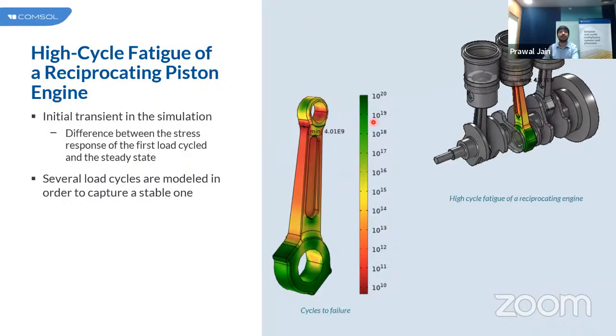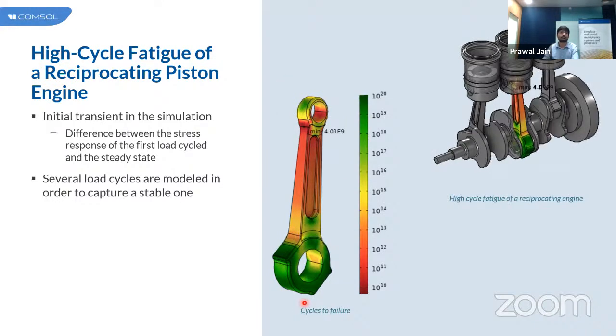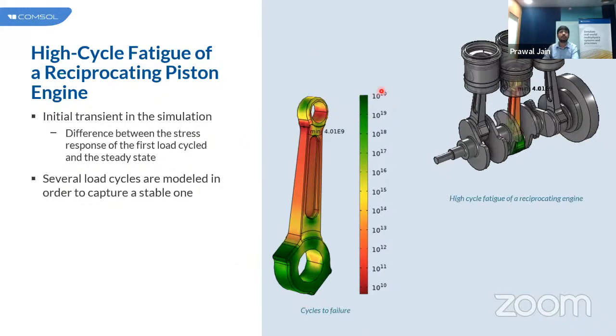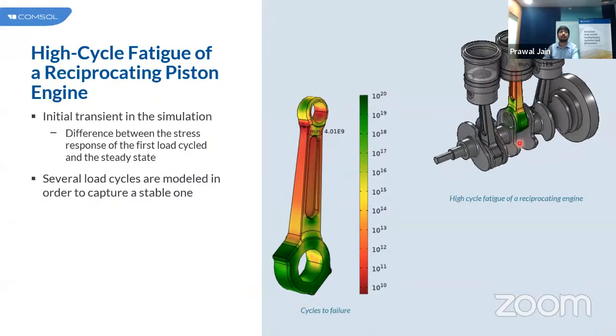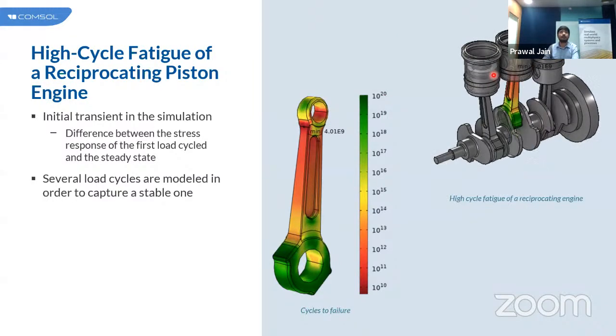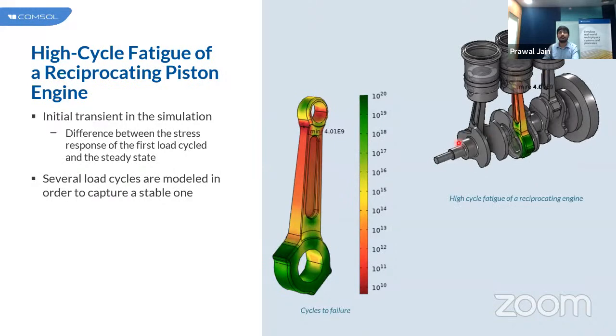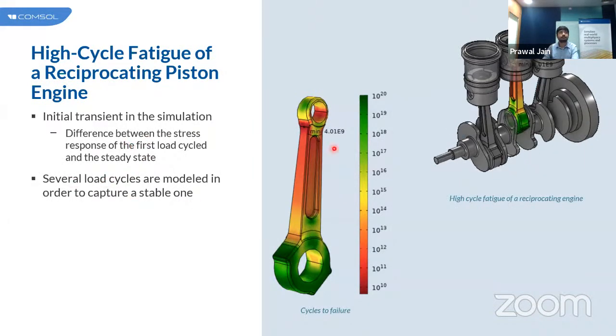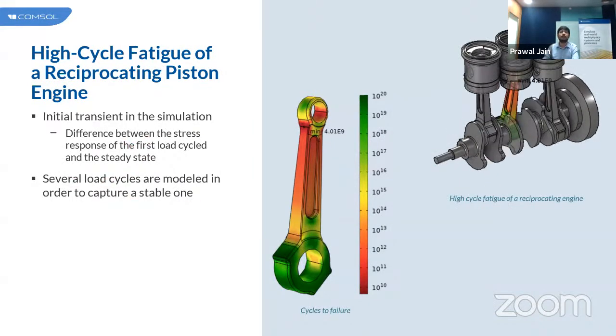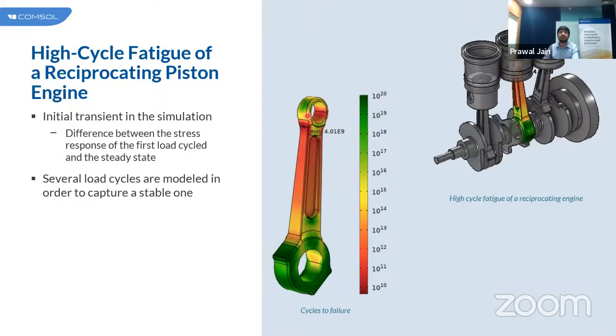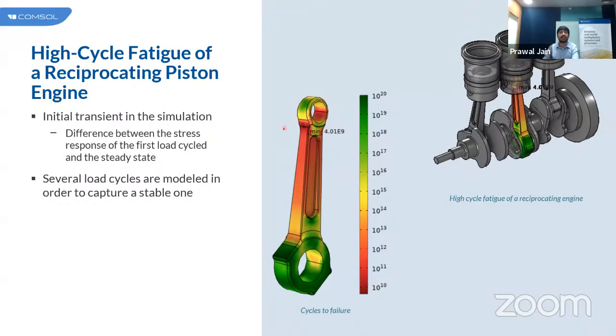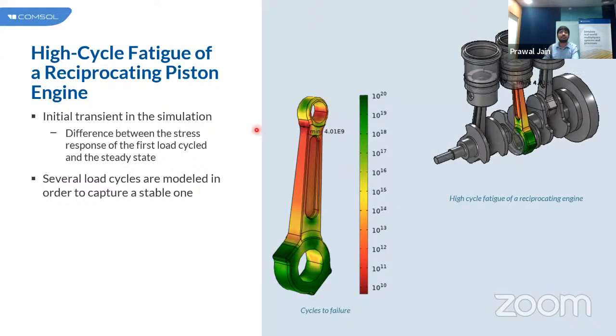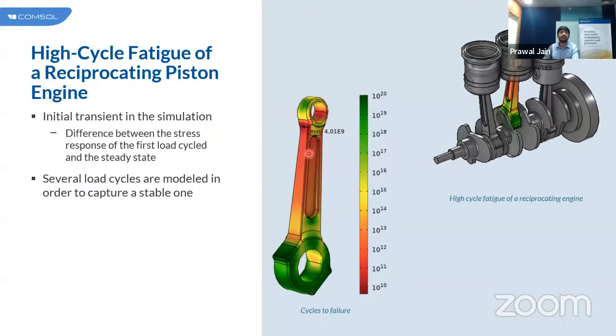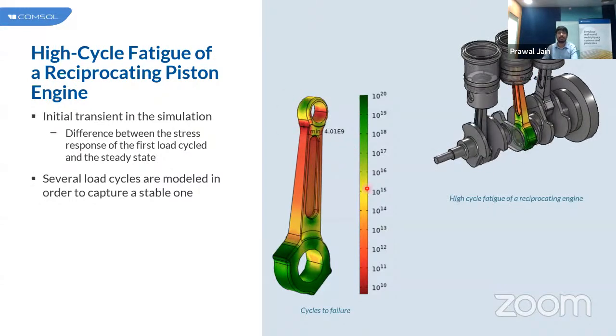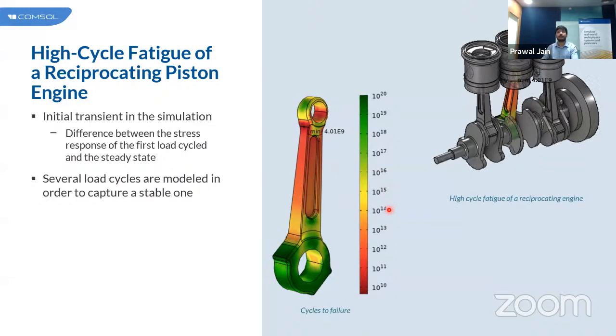So this is basically the fatigue life at various locations of the connecting rod. This is how the fatigue life will be distributed during the whole reciprocating motion. Here the critical point is, as you can see, located at one of the fillets of the connecting rod. Since the stress state is purely uniaxial at that point, the Basquin relation from the stress life family is used to predict the fatigue.